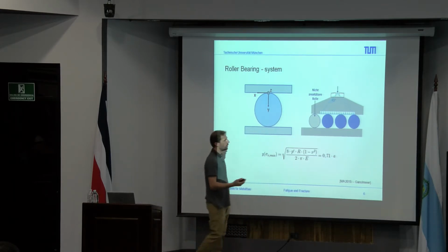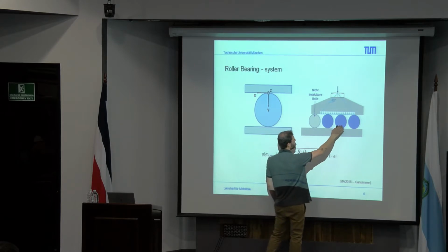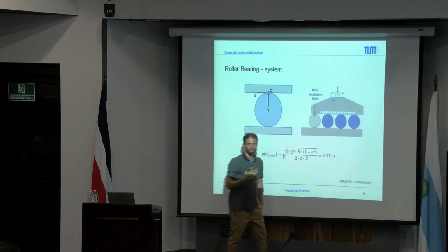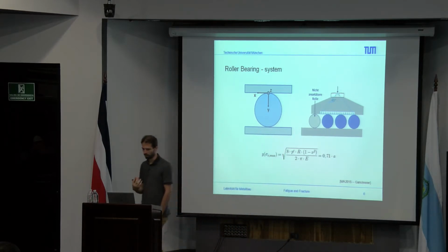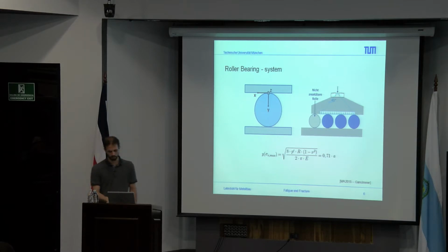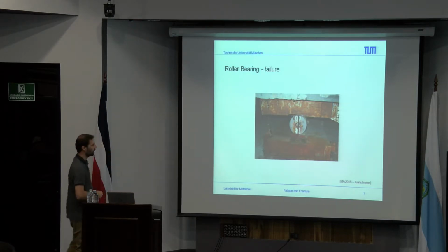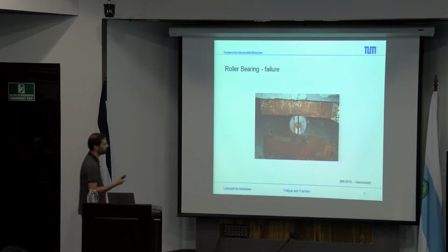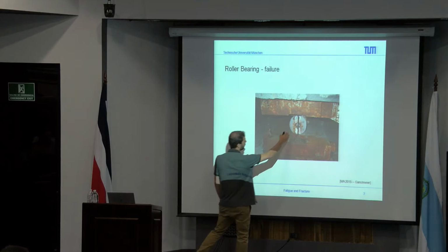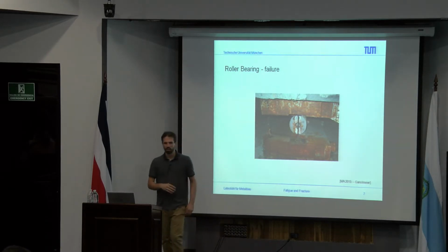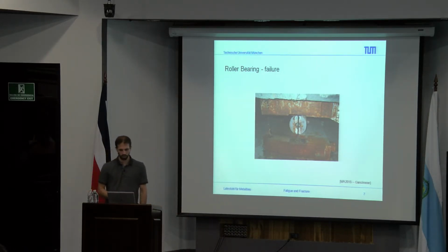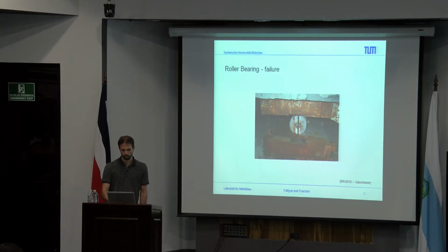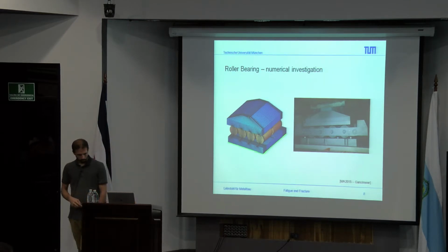So due to the misalignments in the roller bearing, we also said, okay, we have 4 bearings, but just 3 are carrying loads, and the other one is free. So how did it look like, the failures in the 60s? The failures were just splitting up our roller bearing. So at the end you had 2 pieces. If you want to have some load carrying movements also there, you can see, okay, this would not be able.